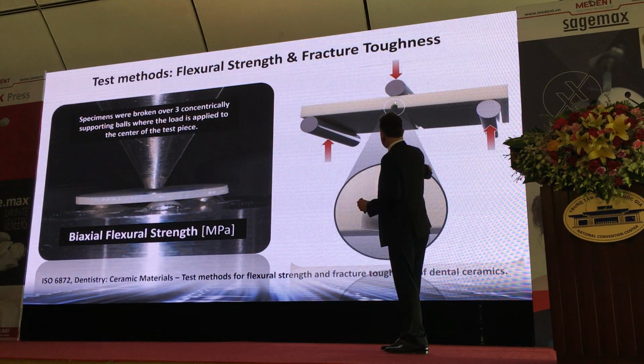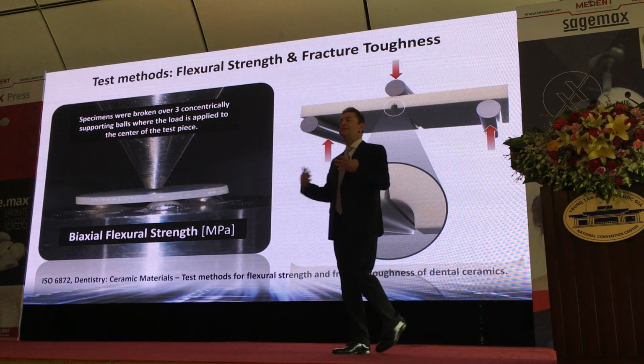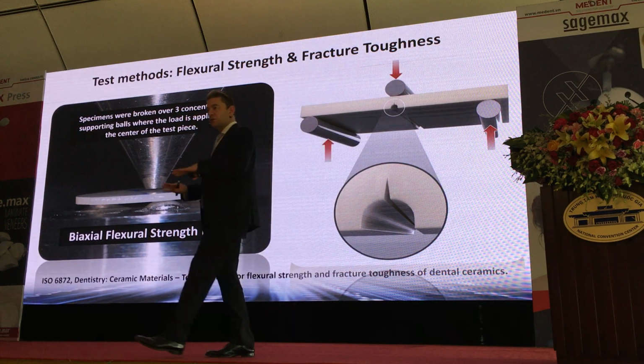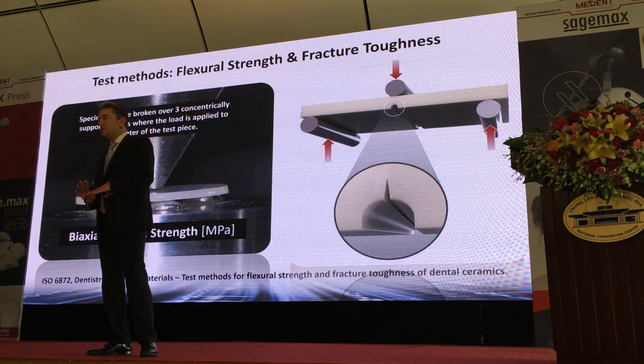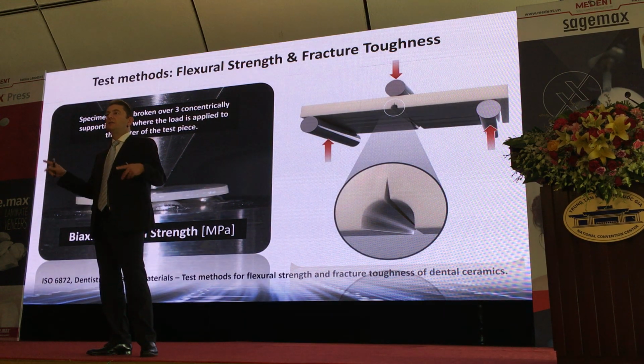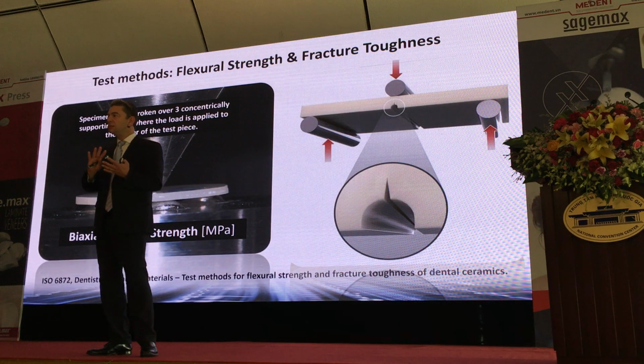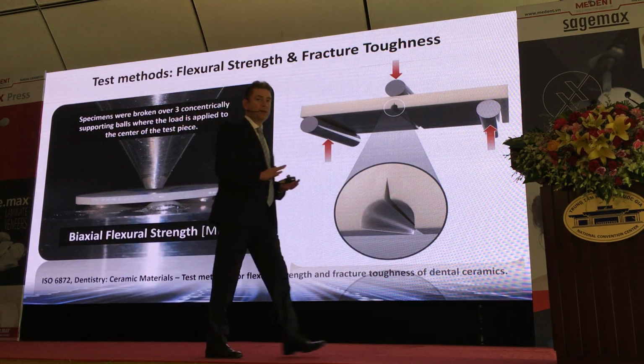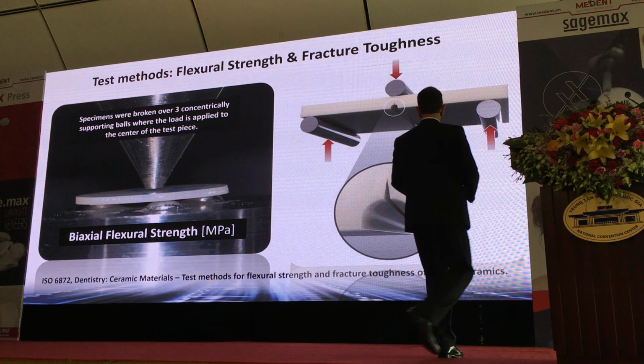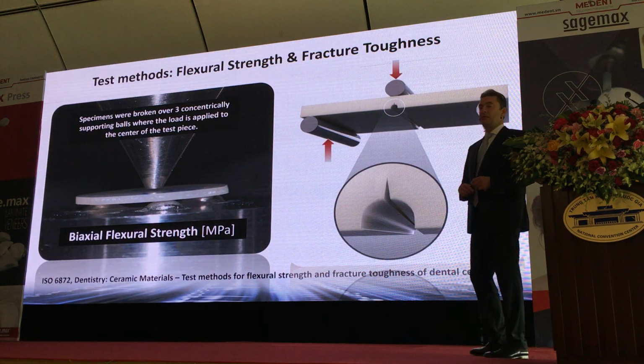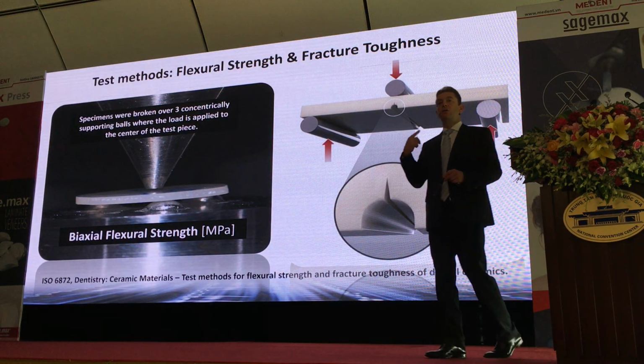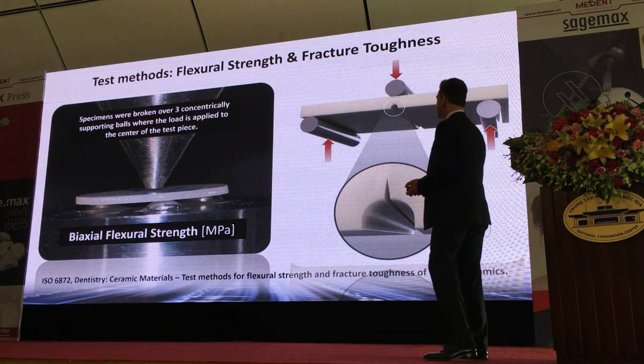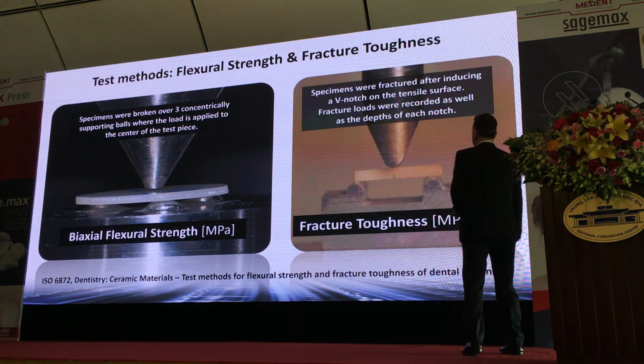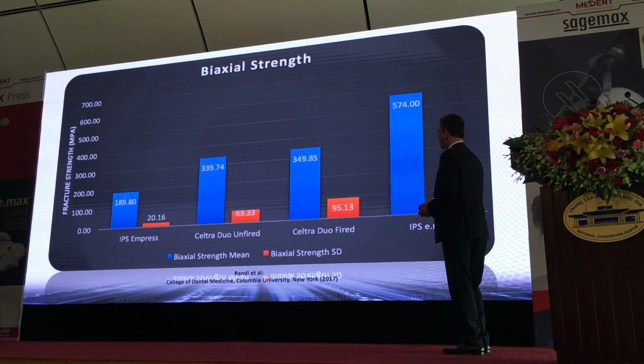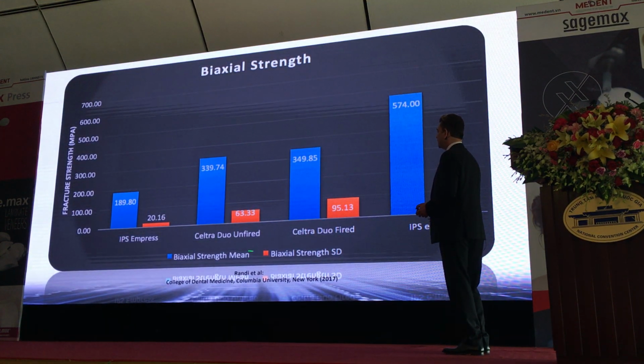Because now this shows you how this crack can propagate inside the material. If the force is very low, it means the crack can easily go through the material. And if the force is very high, it means that the material has a good resistance against this crack propagating. Okay, so now these are the 2 very important tests that are determining the longevity of this restoration in the patient's mouth.